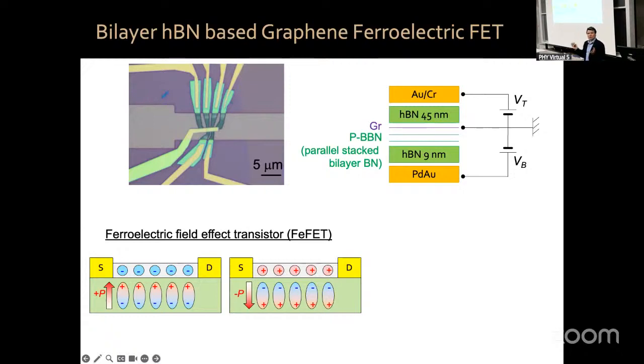Now, since boron nitride is an insulator, we couldn't measure directly in a transport group. My group is an electronic transport group, measuring properties. So what we did is we placed graphene on top, and we made something known as a ferroelectric field effect transistor, where we're looking at how graphene conducts based on what is the ferroelectric polarization state of the ferroelectric underneath.